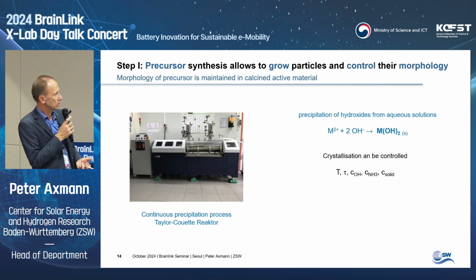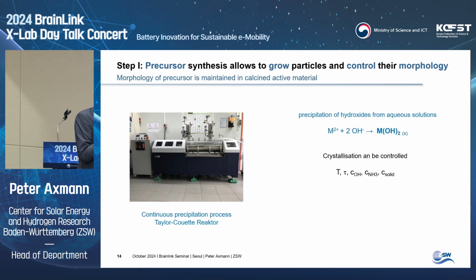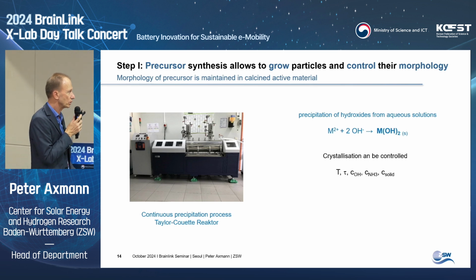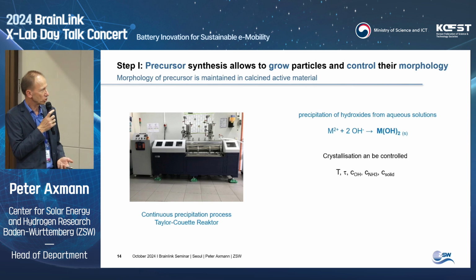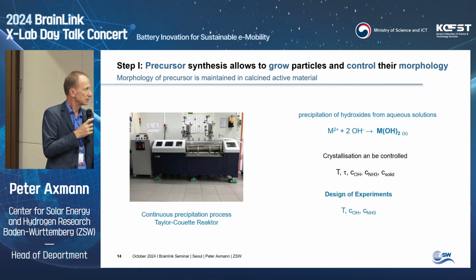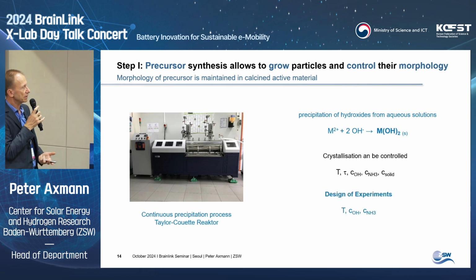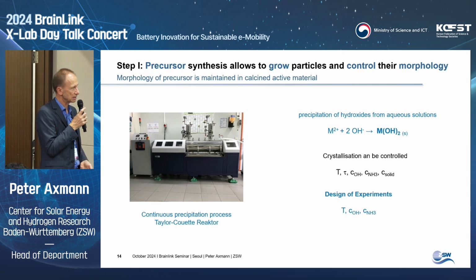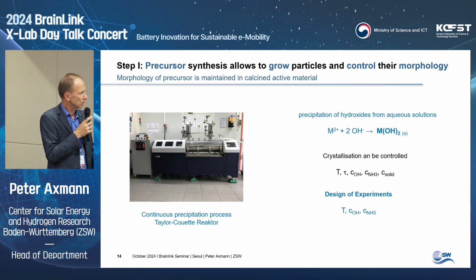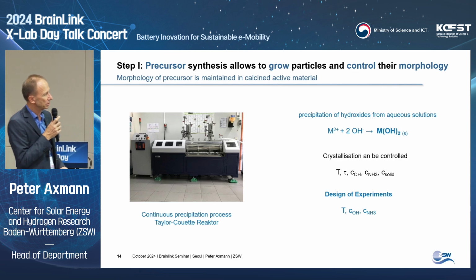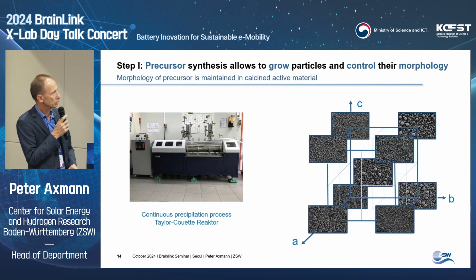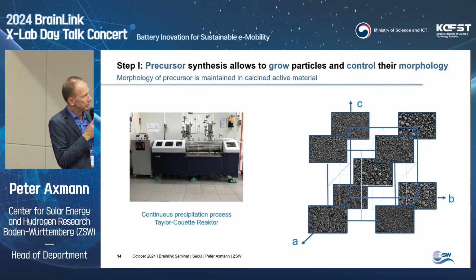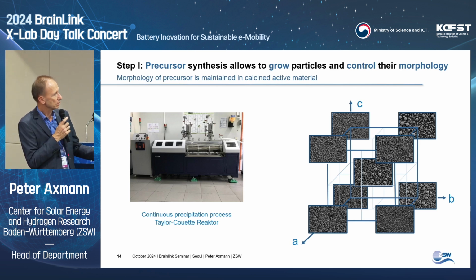But this crystallization can be controlled very nicely. You can change the temperature, you can change the residence time of the materials in the reactor, you can change the pH, you can change the ammonia, which you need for that, and the solid content. By that you have a very large field to optimize the crystallization process and control the particle size. Here is just shown a small design of experiments, changing temperature, pH, and ammonia. And what we see are the SEM pictures you can obtain from these small parts. You see some of the pictures show really nicely spherical particles. Others show more or less small grainy particles.